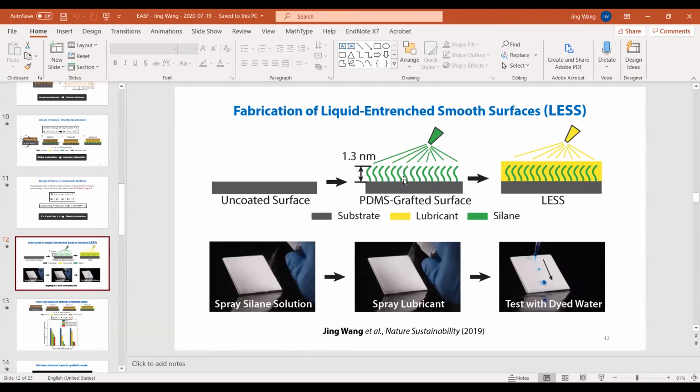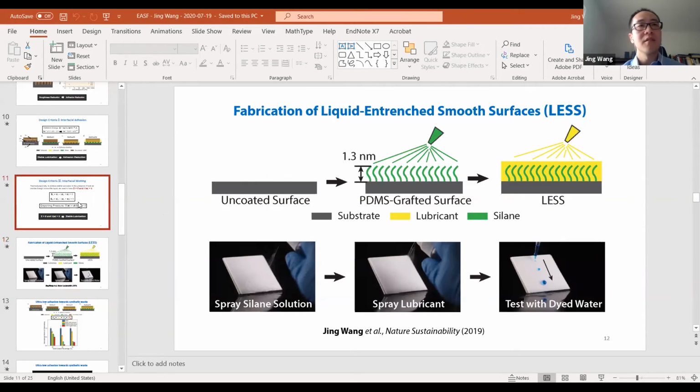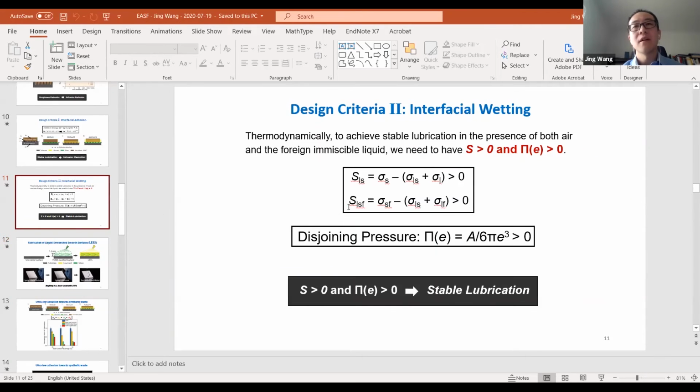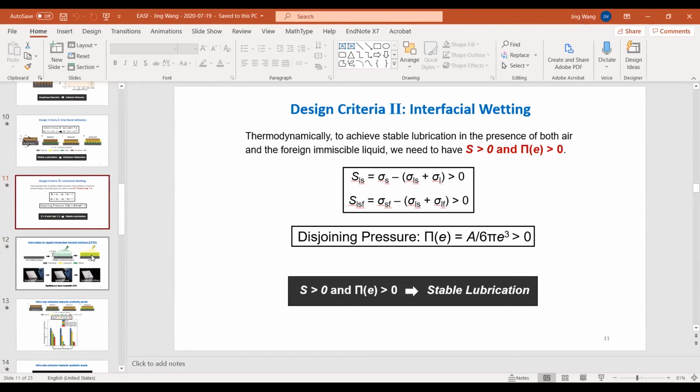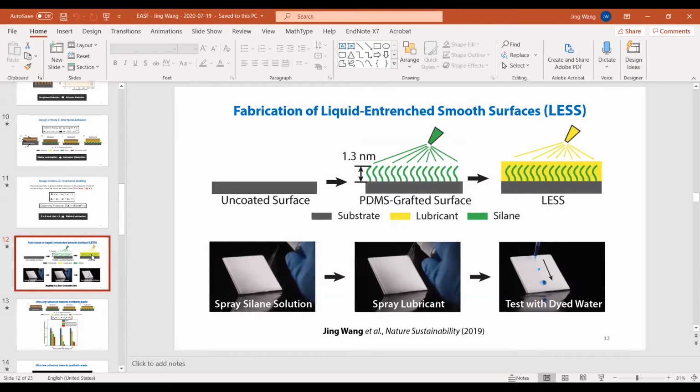So what's the type of your liquid? Sorry, I should mention that the liquid is a PDMS oil as well, so it has the best chemical affinity and will satisfy this criterion, basically. Okay. So because your polymer brush is hydrophobic and your liquid is PDMS, the PDMS can be trapped in the polymer brush.